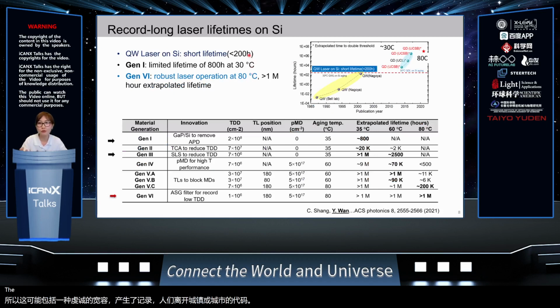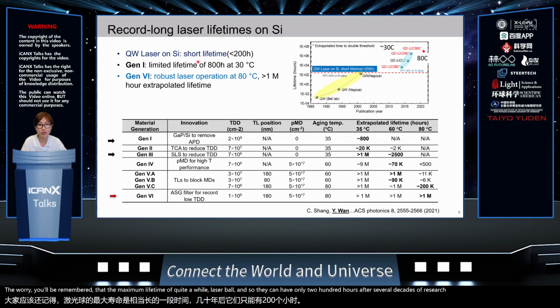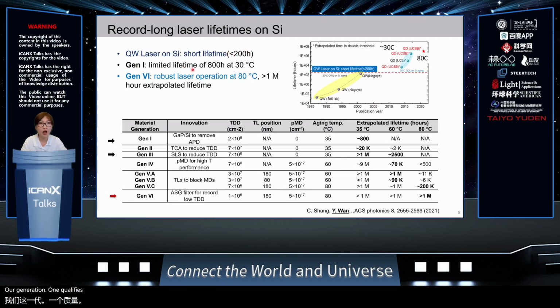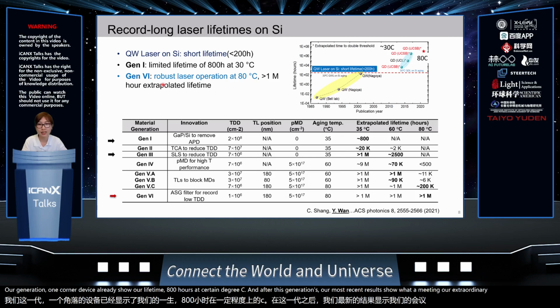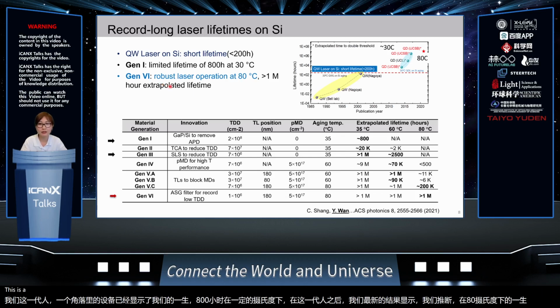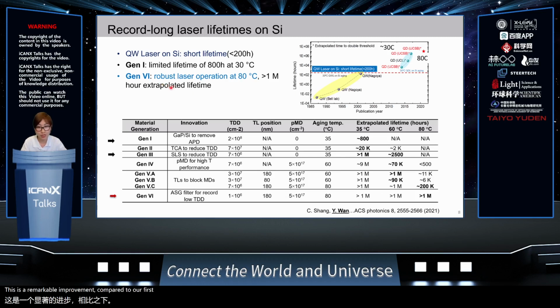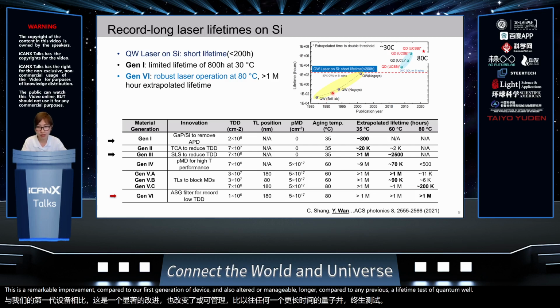Remember that the maximum lifetime of quantum well lasers grown on silicon is only 200 hours after several decades of research. Our generation 1 quantum dot device already showed a lifetime of 800 hours at 30 degrees C. After these generations, our most recent results show a 1 million hour extrapolated lifetime at 80 degrees C. This is a remarkable improvement compared to our first generation of devices, and also orders of magnitude longer compared to any previous lifetime test of quantum well lasers epitaxially grown on a silicon substrate.